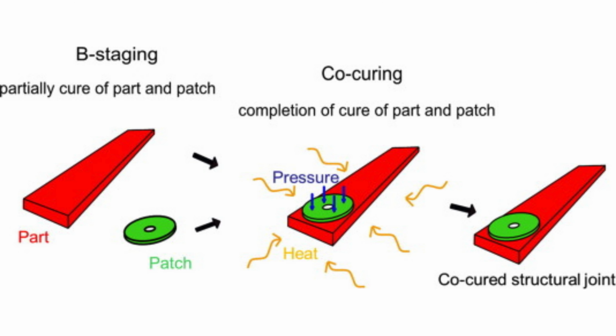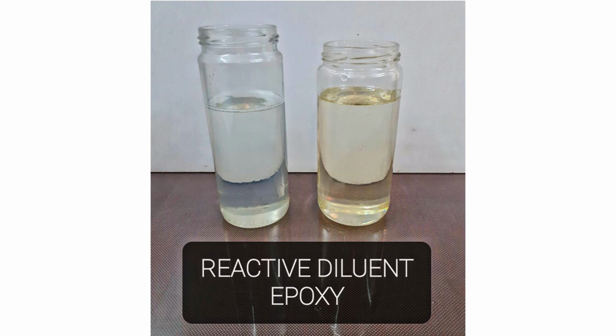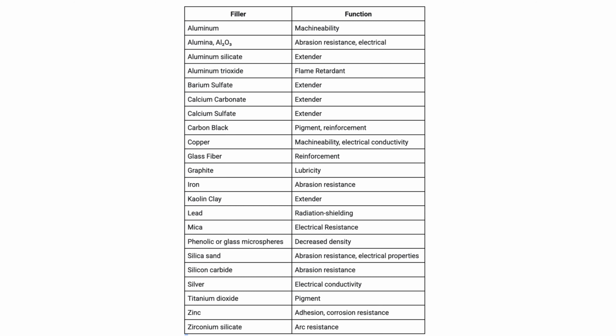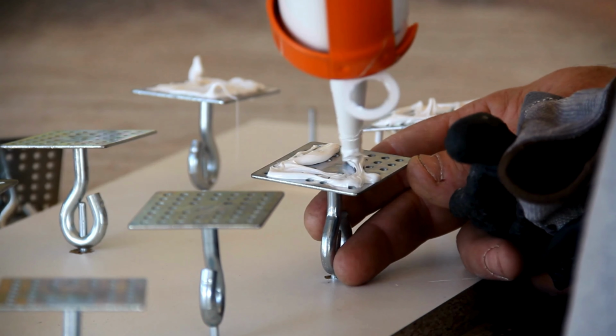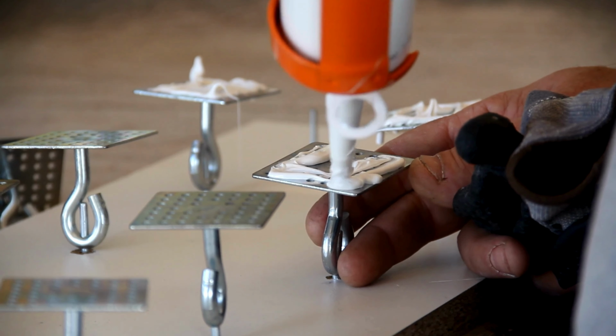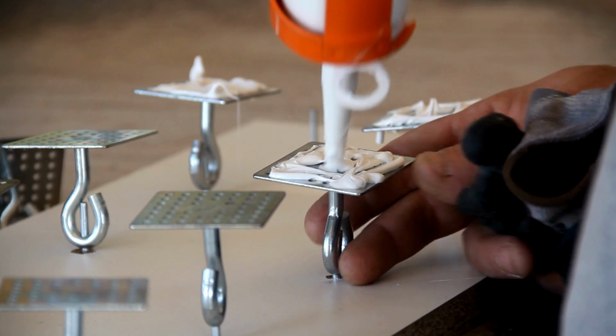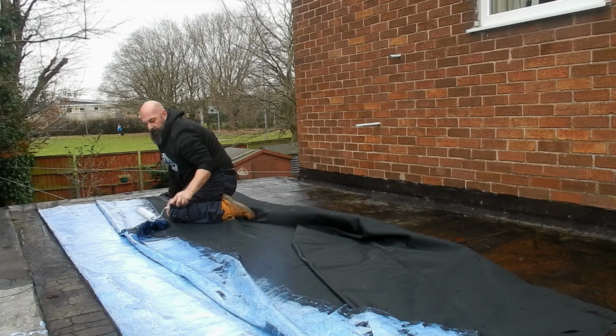Secondary ingredients in epoxy adhesives include reactive diluents to adjust viscosity, mineral fillers to lower cost, adjust viscosity, or modify the coefficient of thermal expansion, and fibrous fillers to improve thixotropy and cohesive strength. Epoxy resins are often modified with other resins to enhance certain properties that are necessary for the application. Often these modifications take the form of additions of elastomeric resins to improve toughness or peel strength.